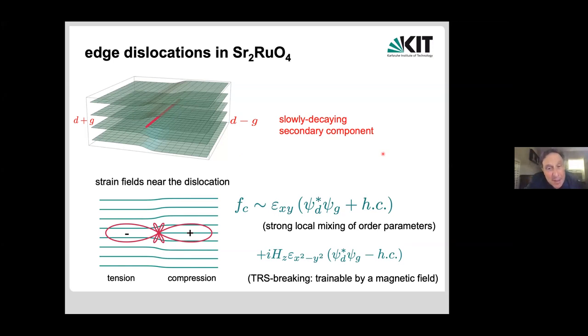Okay, good. So first of all, it seems to me that probably these are not totally distinct proposals, that somehow for the G component to be significant with the strain, it has to be close to ordering on its own. Correct. But I had a specific question. Presumably, it should be possible to change the concentration of dislocations. Even if one can't get rid of them, one could purposely introduce more dislocations to see whether dislocations are playing a key role. In that sense, this is a falsifiable scenario, but I believe this has not been done. Just to complement Steve, this may be possible using plastic deformation. Yeah, because then you go beyond, anyway. Convince the experimentalists to wreck their beautiful crystals.